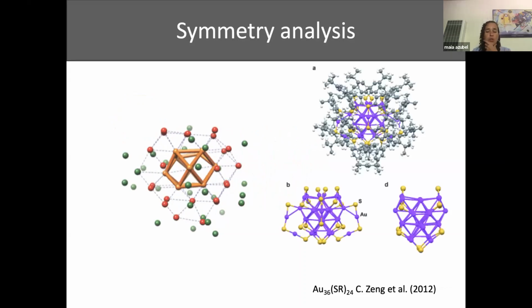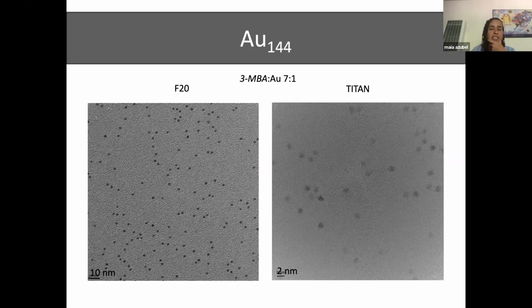Luckily, there was another cluster that was solved at that time or a little bit before us that also has an FCC-like symmetry. So we knew that there were a lot of things that were together for us. And the other cluster that I mentioned is what I call the 3 MBA 7, and it turned out to be the 144, but not the 144 that people were working with organic thiols or with the PMBA. This is again slightly different because of the use of the 3 MBA. But what you are seeing here are 2 images, one of the F20. The F20 is the one that doesn't have the correction, and in that case, you will not be able to see the individual atoms. The magnification also is much lower, but you can see how nice and homogeneous they are.